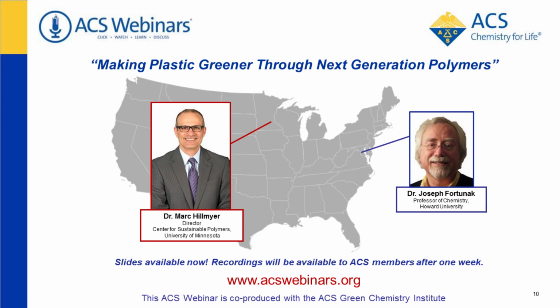So having a more hydrophobic material actually limits and mitigates the amount of water absorption in the material, which will then slow down that rate of hydrolysis. Moreover, people in the PLA field are certainly keen on making highly crystalline PLA, which slows down the hydrolysis, and even something called a stereocomplex, which I mentioned in Jeff's work, a stereocomplex that can have a very high melting point and can also be beneficial from the standpoint of slowing hydrolysis.